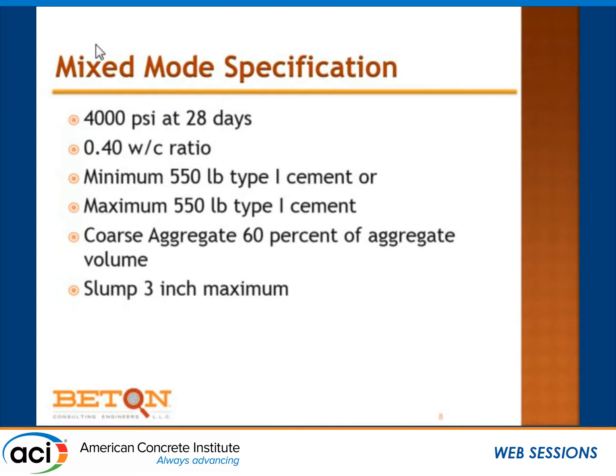We designed the structure. We wanted to have a certain strength, and C31 and C39 are going to let us check. We're also going to indicate that you are going to cite ACI 301, which says that the 4,000 PSI really isn't 4,000, it's some larger number depending on how variable we think things are going to be. We're going to have a water-to-cement ratio, and that can be specified for a lot of reasons, but the water-to-cement ratio, as we will probably remember, is tied to the strength. So we can write them down independently, but nature tells us that that's not the way we're allowed to do things.